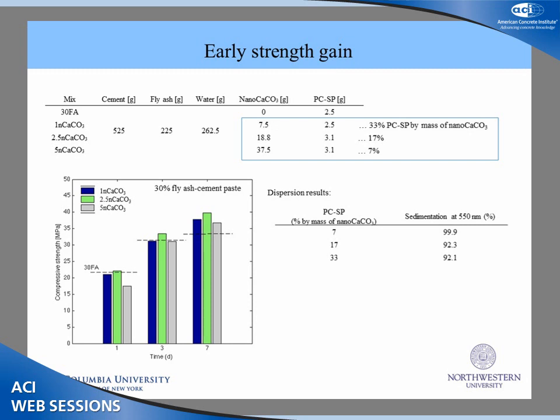And so if we add an excess amount, the paste is going to exhibit segregation. So our PC dosage was limited by the rheology of our material, and so we had to keep it at 3.1. And this yielded a 7% dosage by mass of nanocalcium carbonate.